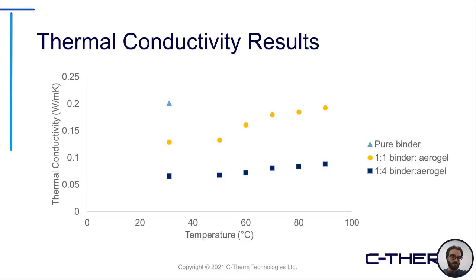Now, on top of that, when investigating the influence of temperature, again, this trend held true across the different temperature points of interest. As we can see, the sample noted with the dark blue squares had the higher concentration of the aerogel material and overall the lowest thermal conductivity measurement compared to the other material. So this is an example of how you can incorporate some of these materials into the overall build to, in this case, decrease the effective measurement.